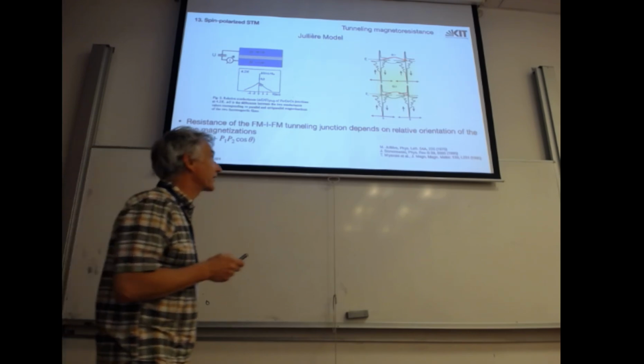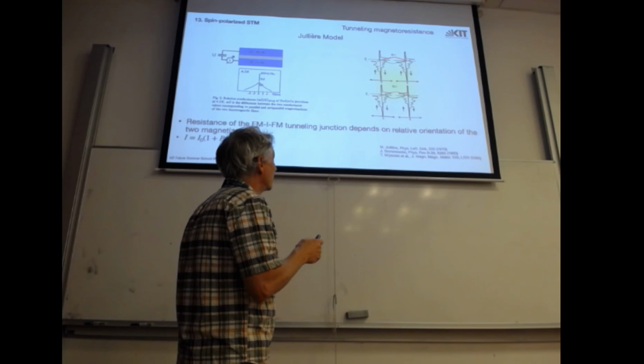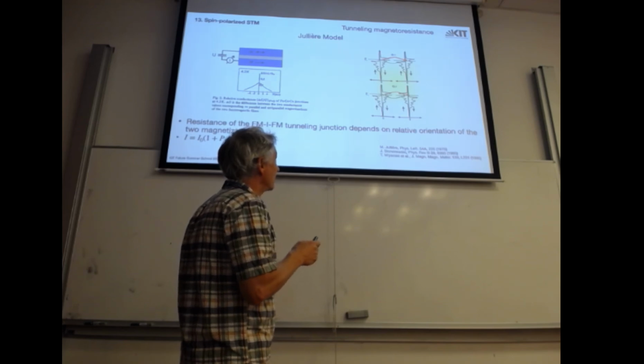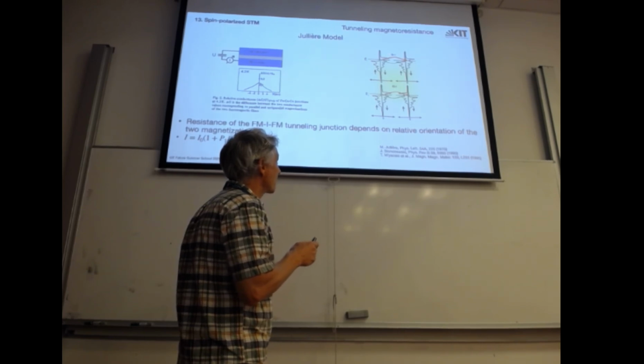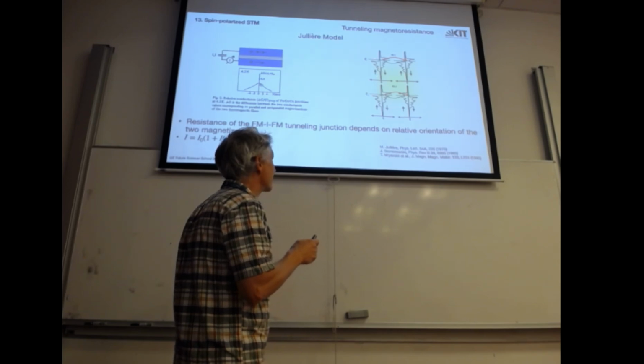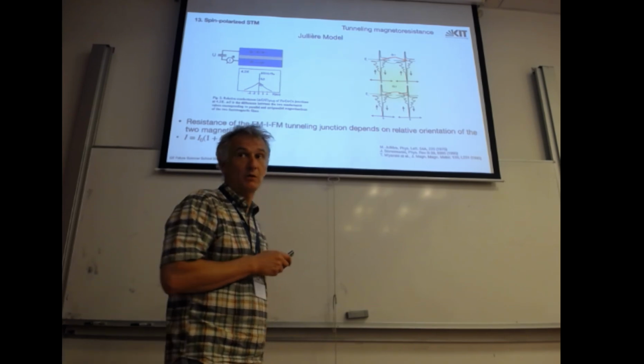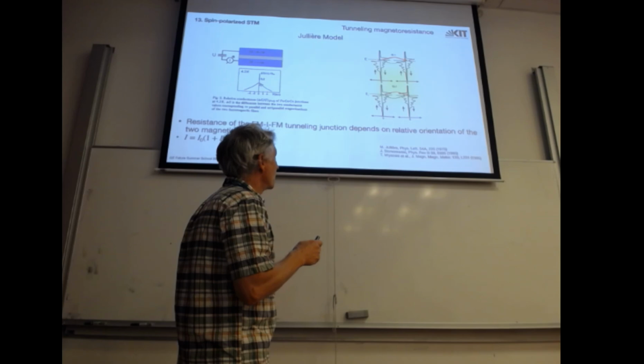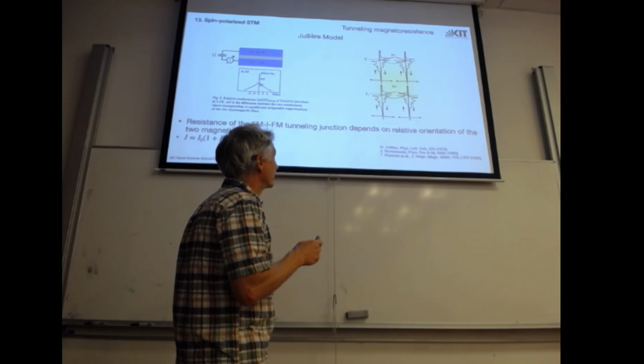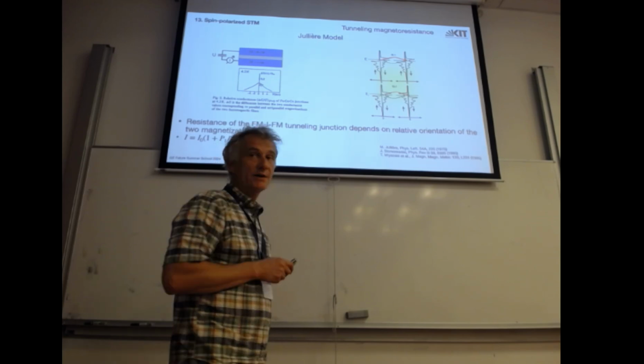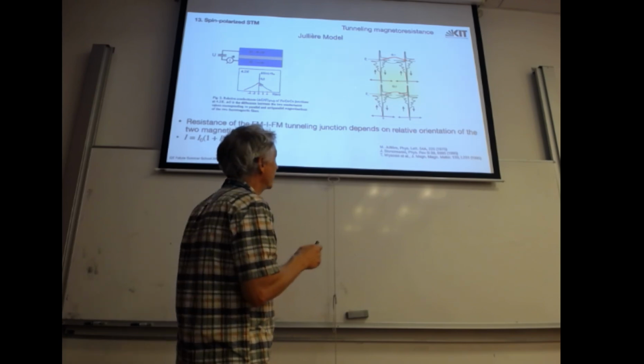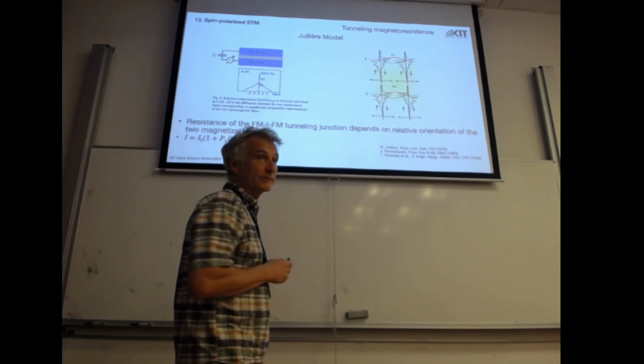So spin-orbit interaction is small. Then, if the two electrons are parallel, I go from majority states to majority states. So this is called density of states. Majority is defined from magnetization, but the density of states at the Fermi energy is actually small. So we go from the small one to the small one, and from minority electrons, which have a large density at the Fermi edge, to a large one.